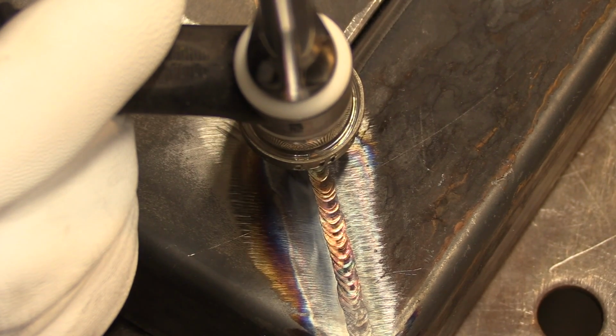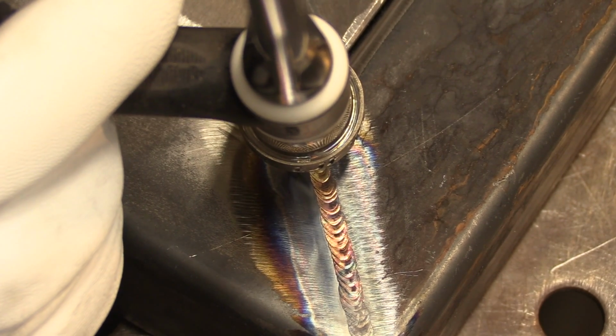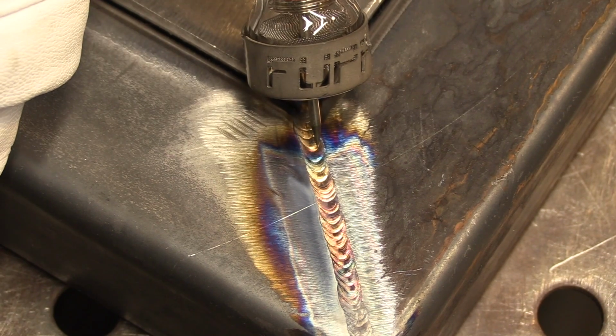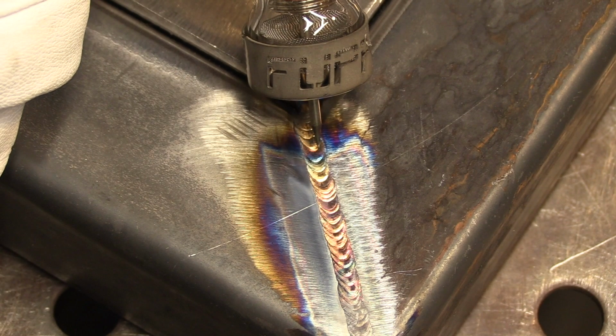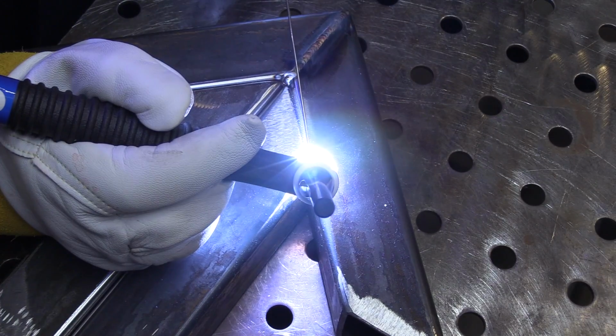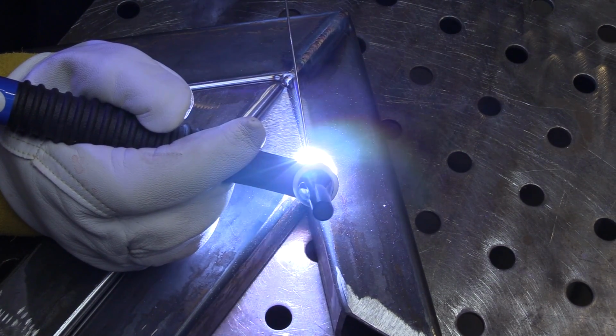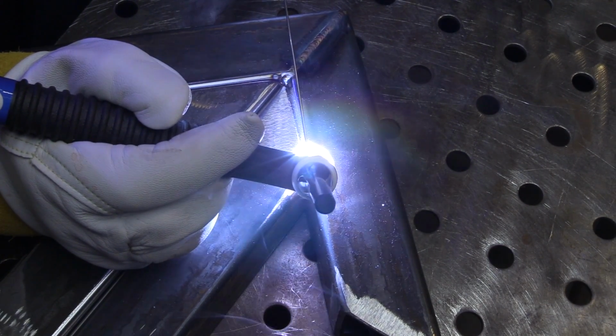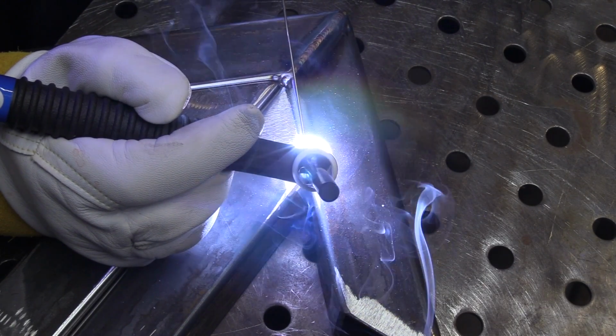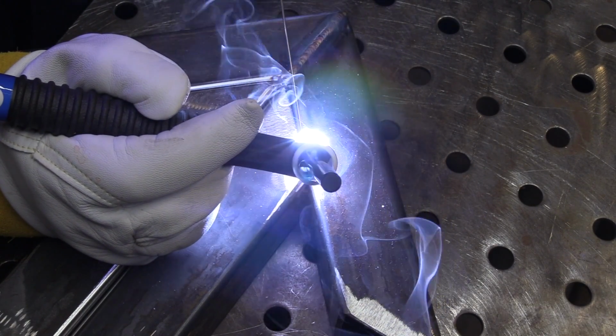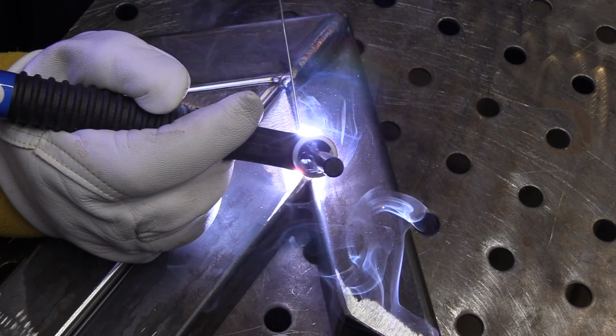So I'll take this bead all the way down into that corner tack before I taper off. And I'll hold the post-flow shielding over there several seconds. Now, having the post-flow on for a long time is not necessary on carbon steel. It only really makes a difference when you're going to restart on a bead. Usually carbon steel will be painted after the fact or something like that, so you're just wasting gas a lot of times to set your post-flow on 15 seconds or something on carbon.